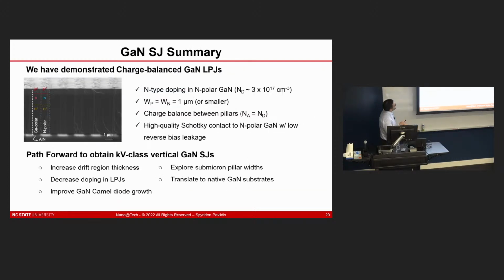So this is a very unique approach to making these super junction structures with these lateral polar junctions. Up until now, we had not been able to demonstrate charge balance between these, and so that's a major development in this area. As I mentioned earlier, when we're just growing nitrogen polar GaN, we can see the low 1E17s doping. We're working to try to get that alongside charge balancing in the lateral polar junctions.